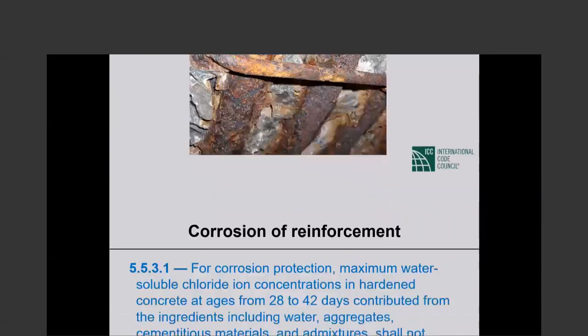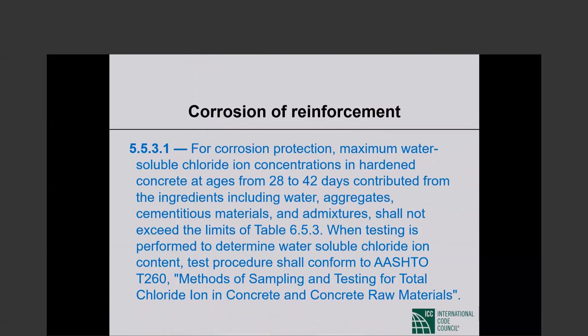Corrosion resistance, again, the topic came up, but this is further on that. For corrosion protection, maximum water soluble. So previously we told you that the water cement ratio has to be limited to whatever value. Now we are going further, and this is extremely important. For corrosion protection, maximum water-soluble chloride ion concentrations in hardened concrete at ages from 28 to 42 days, contributed from the ingredients including water, aggregates, cementitious materials, and admixtures, shall not exceed the limits given. That is a table. So if you have a corrosion problem, the chlorides from all sources have to be limited to values given in the table.